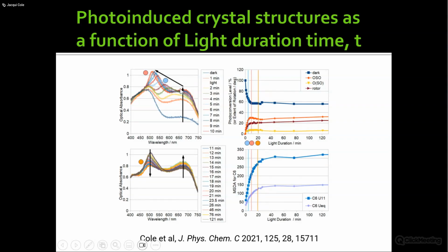And these circles I drew just to give you an idea of how this correlates to the photoconversion level from the structural side, right? So this is the photoconversion level we've seen in the previous slides. So really quite quickly in this case, we're already at this. So we've already risen in optical absorption and had some solvatochromic shift, if you like, to this point within a very, very short period of time, right? And that basically correlates with the rise in the rotor. That's the arene ring that's converting. And you see the corresponding real drop in the dark state.